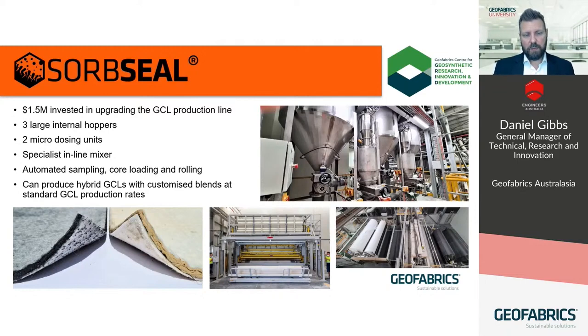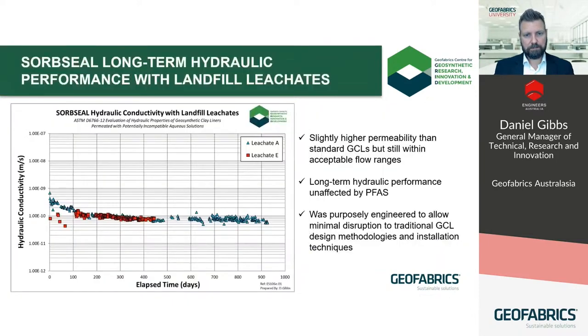So we added 3 separate large hoppers for powders and also 2 special microdosing units for any polymers or other materials which we found to be effective in trapping long and short chain PFAS at low addition rates. We installed an automated sampling unit as well as a new core loading and rolling system. And this gave us a longer roll length capacity. And all of this really resulted in a great deal of future-proofed manufacturing and product design flexibility. The final result was a hybrid GCL product, which we named SorbSeal.